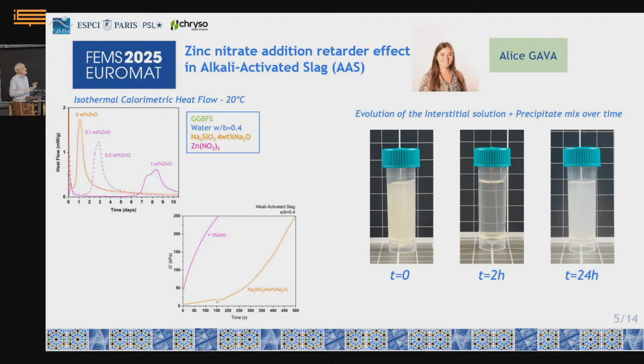But our intuition is that everything is linked to this idea of how much silicate I have in solution initially when the reaction starts, and how the system phase separates. Is it waiting for nucleation and growth, or is it immediately proceeding into a precipitation and amorphous gel? Okay? And so in our opinion, the way to control this is by temporarily engaging the silicate, and certainly not by seeding or things like that, because there is nothing to seed here, because there is nothing to nucleate. So it's very different from the ordinary Portland cement case. I'm sorry I was too long.